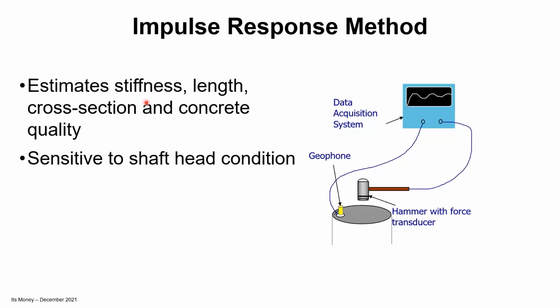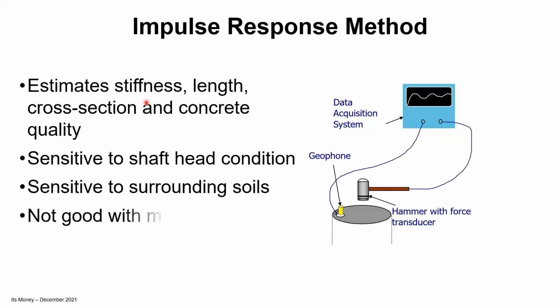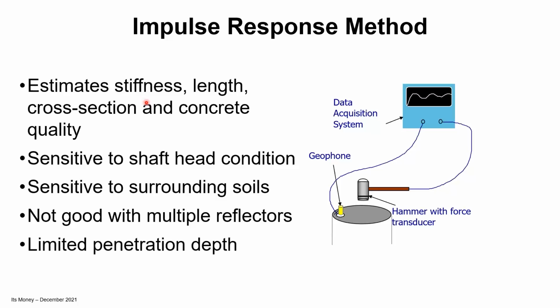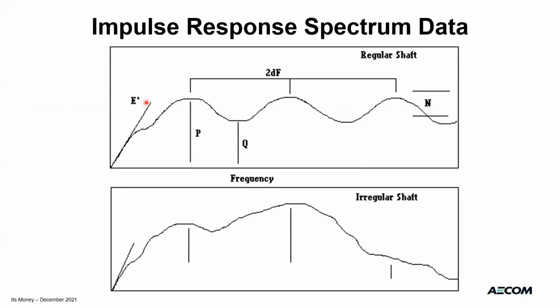It's very sensitive to the shaft head condition because of the force transducer. If the head crumbles as we hit it, if the concrete's cracked or broken or contaminated, it'll distort the force measurement, and so it will skew the response when we try to calculate stiffness. It's still sensitive to surrounding soils in the same way that the impulse echo test is, and it's still not very good with multiple reflectors. Same limited penetration depth, but we get extra data because of the force measurement that enables us to do a frequency analysis where we get several pieces of information out of the curve instead of just the time.